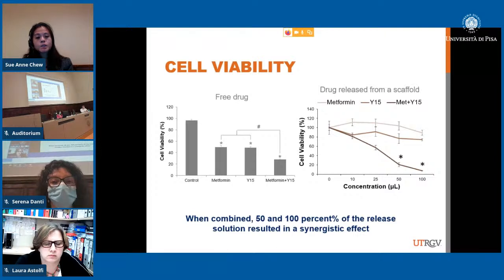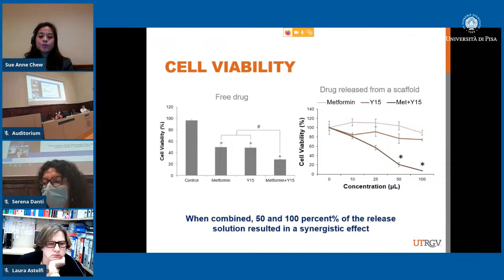So on the left here, I'm showing you the free drug, the work that was done previously on the 2D culture, where drugs in solution were exposed to the cells, right? There was a nice synergistic effect. But you see on the right, when we release the drugs from these scaffolds that we made, we see an even more improved synergistic effect. I say that because with the solo drug itself, there wasn't much effect. If we do the statistics, it's comparable to the control. But amazingly, when you combine these two together, we see that synergistic effect. For both, when we use 100% of the release solution or 50%, meaning we dilute the solution with 50% media, we still see that synergistic effect.